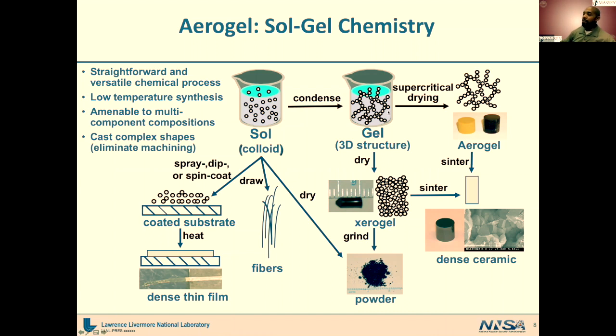And so when you have this solid gel network within the liquid, you then have various options in order to get a dry material. You can directly dry that ambiently. And what will happen is, because the pores, as I mentioned before, are very small within the gel, you'll get a collapsing of those pores due to capillary pressure as you're drawing off the liquid. Many times we do that on purpose to get a condensed structure, which we can then sinter to full density to make very dense ceramics.